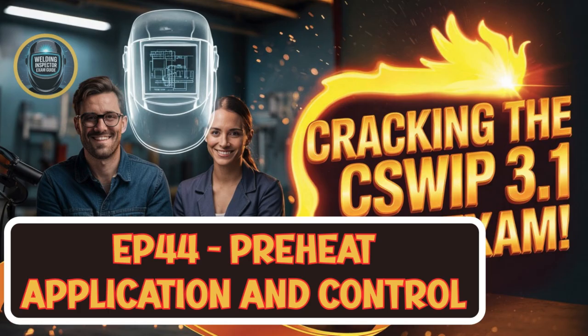And importantly, wherever practical, the source says you should try to measure on the face opposite to the one being heated. Opposite. Why is that? To make sure the heat has soaked all the way through the thickness, not just heated the surface where the torch was. Ensures a deep, even heat. Exactly. And that ties into another key point. You need to allow time for the temperature to equalize. A common rule of thumb mentioned is about 2 minutes for every 25 millimeters of thickness. 2 minutes per inch, basically. Roughly, yeah. You need that time for the heat to distribute evenly through the metal. If you measure too soon, especially with flame heating, you might just be reading the surface temperature, which could be much higher than the core temperature. That gives you a misleading, potentially unsafe reading.